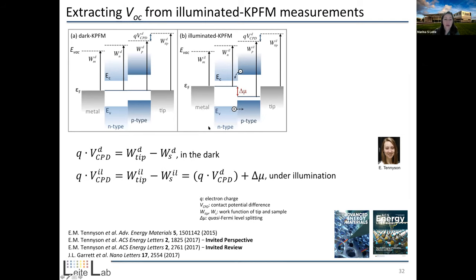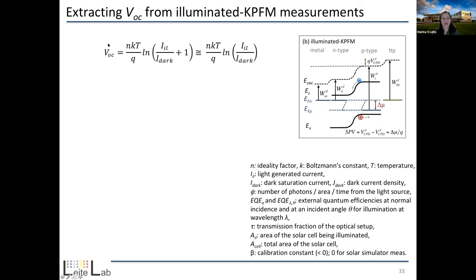So once we did that, we're still measuring a difference in work function between the tip and, now under illumination, the surface of the sample. However, if you subtract the two signals, we actually have the splitting of the quasi Fermi level, which is directly proportional to our open circuit voltage. So if we do that, we can now resolve and quantify how much contribution we have to the VOC at the nanoscale.